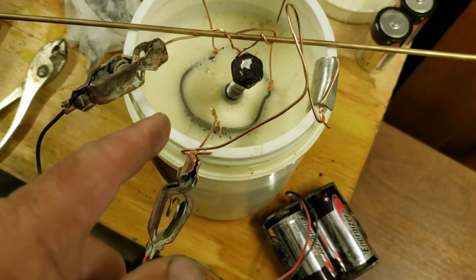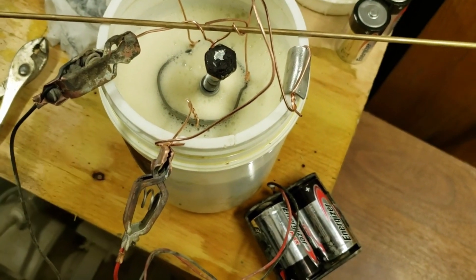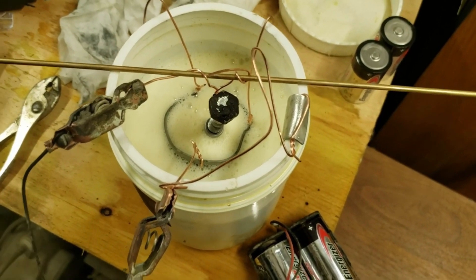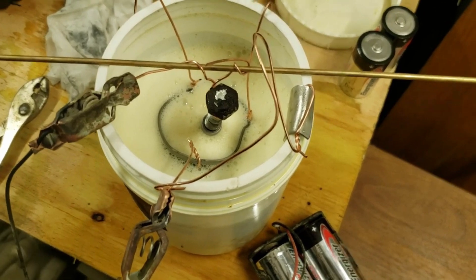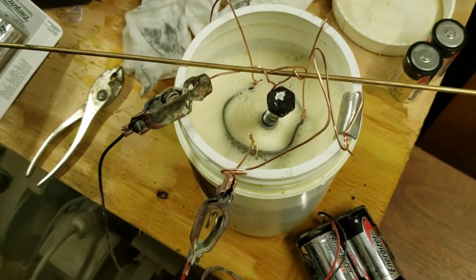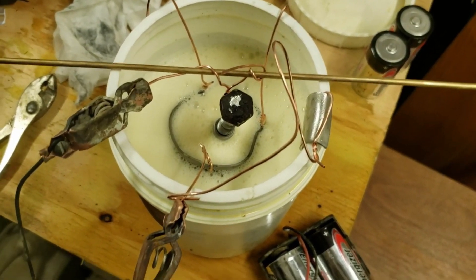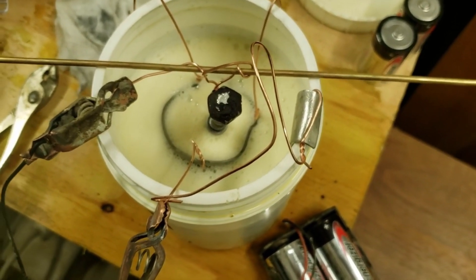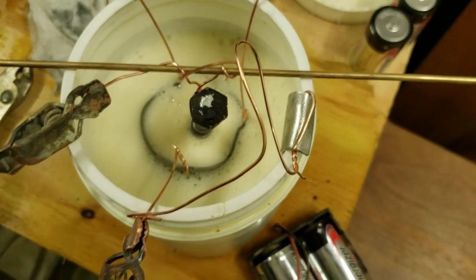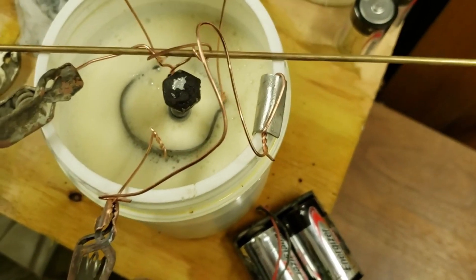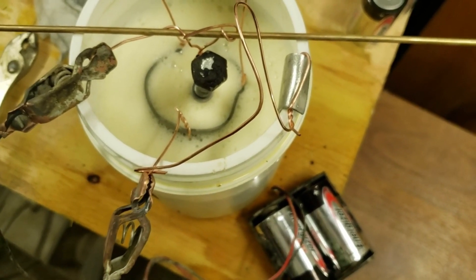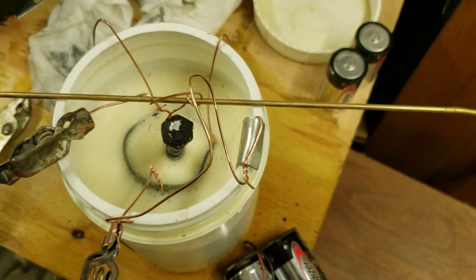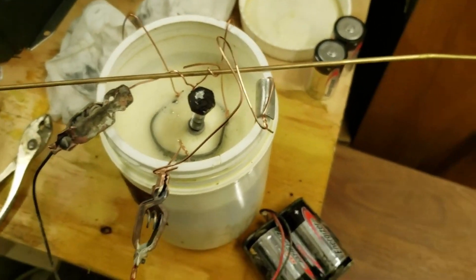Okay, I didn't film it but I pulled the bowl out, I rinsed it off, and I rubbed it down lightly with really fine triple-ought steel wool. You get a little bit of a crusty build-up sometimes, so it doesn't zinc plate quite as thick when it does that. So by cleaning it all off, prepping it up real nice again without removing any of the new zinc, and then putting it back in, we'll give it an extra coat of zinc here.